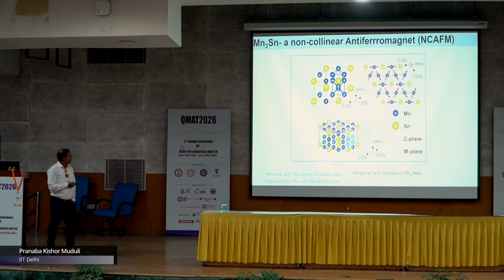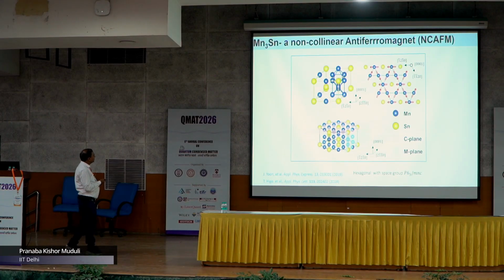Okay, now I will go to the material that I want to discuss, and this is Mn3Sn. It is a non-collinear antiferromagnet. The crystal structure is hexagonal, with this space group symmetry. If you look at the c-plane, which has hexagonal symmetry, you have this kind of inverse triangular structure. This is also known as the Kagome lattice.